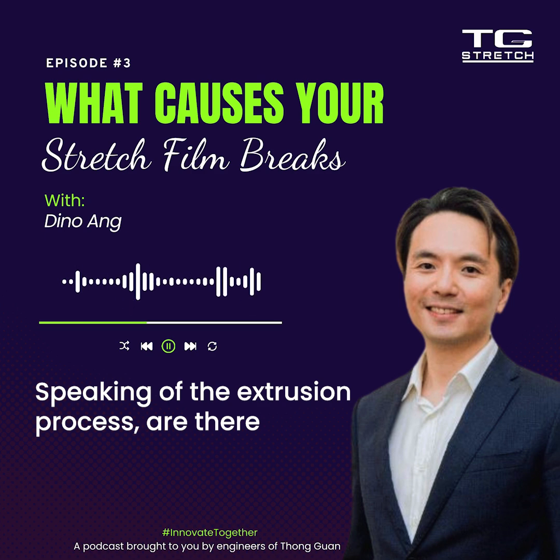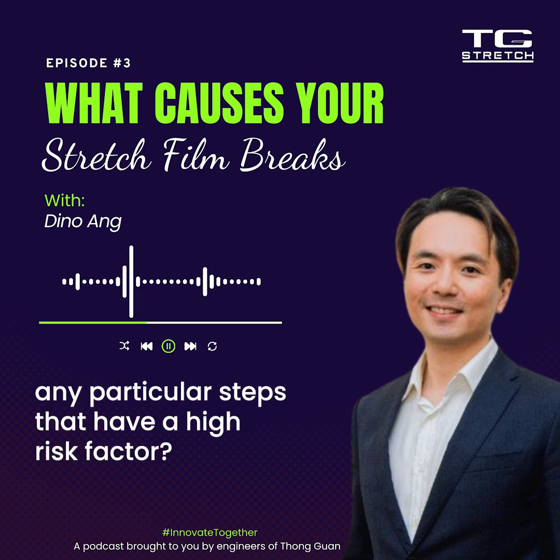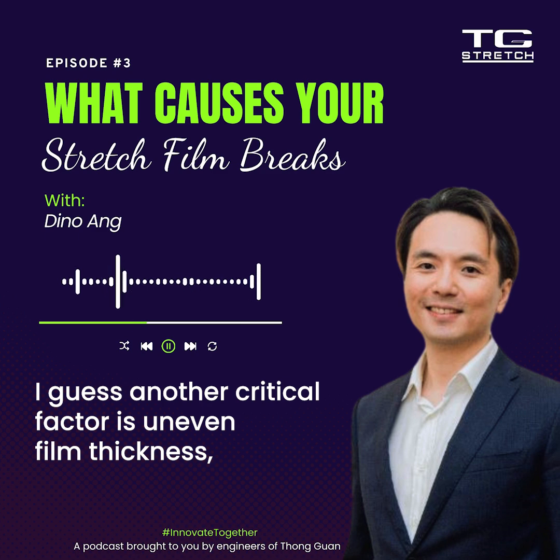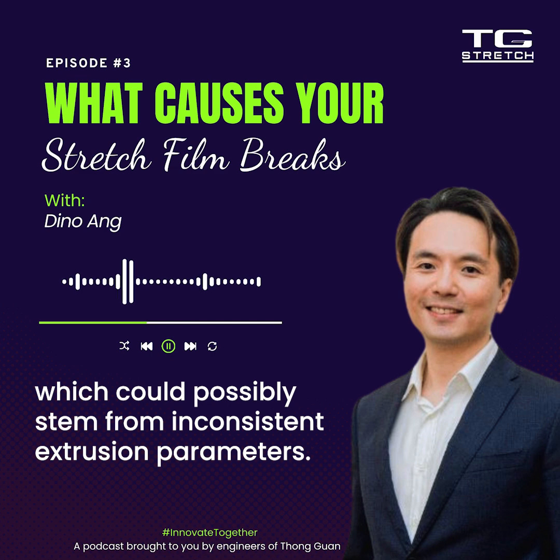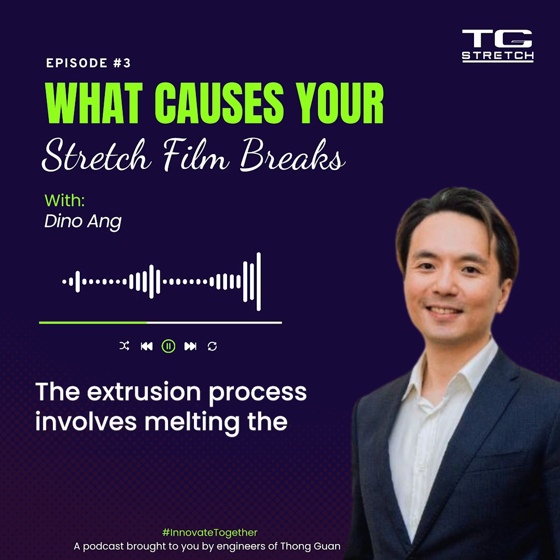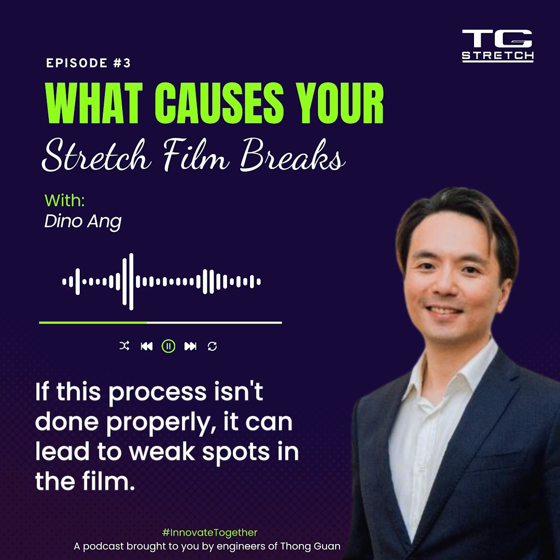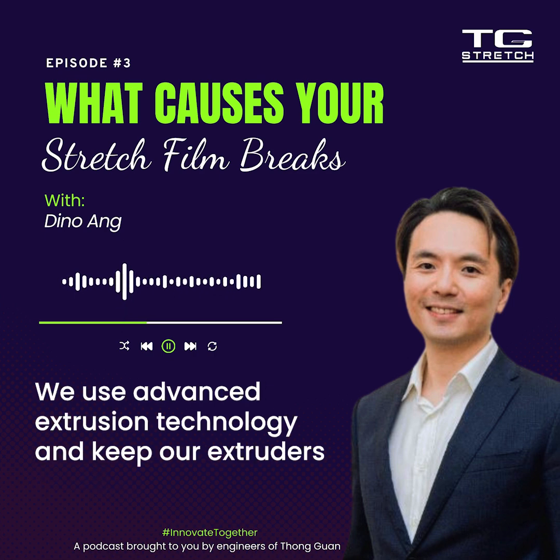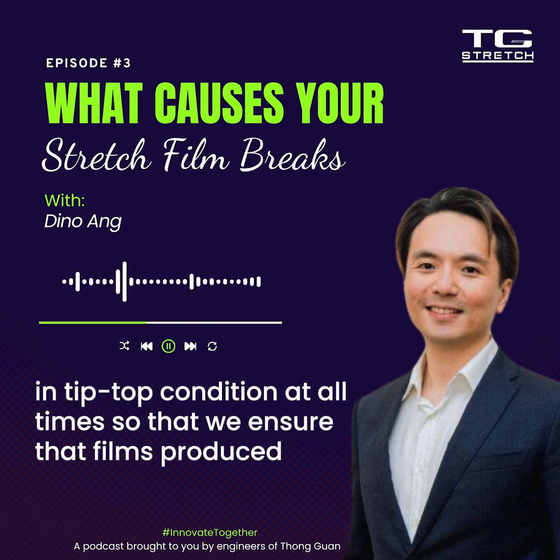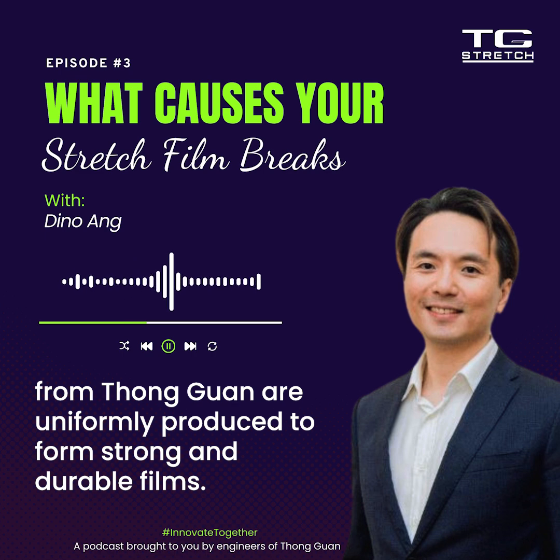Speaking of the extrusion process, are there any particular steps that have a high risk factor? I guess another critical factor is uneven film thickness, which could possibly stem from inconsistent extrusion parameters. The extrusion process involves melting the resins and extruding them into thin films. If this process isn't done properly, it can lead to weak spots in the film. We use advanced extrusion technology and keep our extruders in tip-top condition at all times so that films produced from Thong Guan are uniformly produced to form strong and durable films.